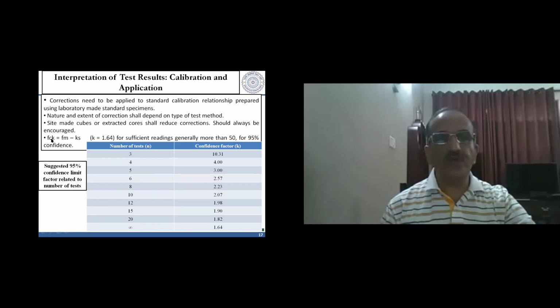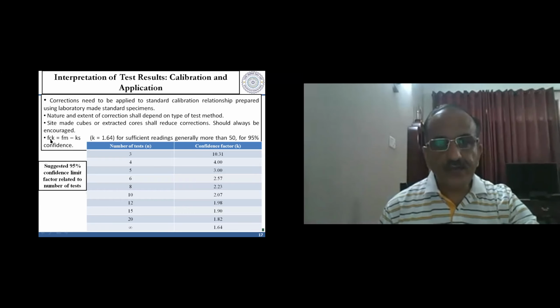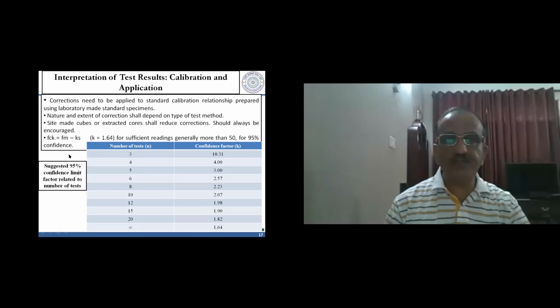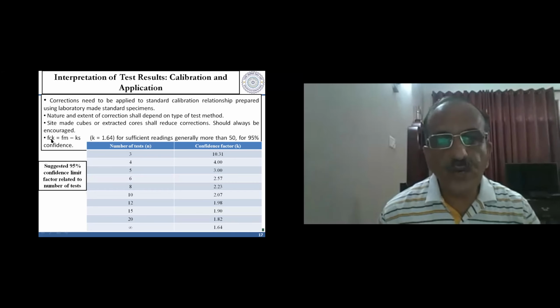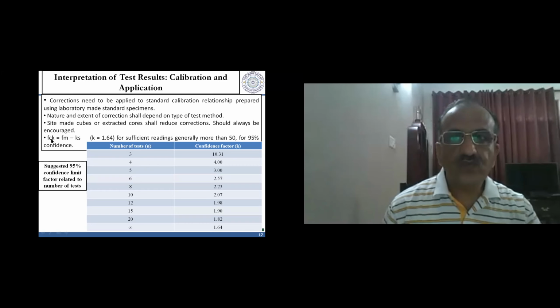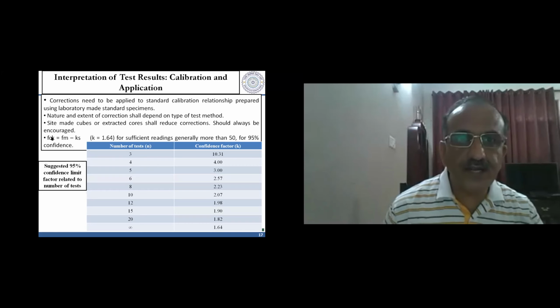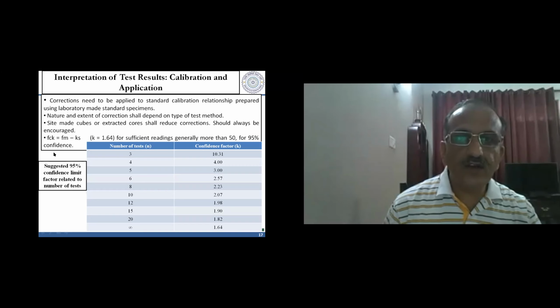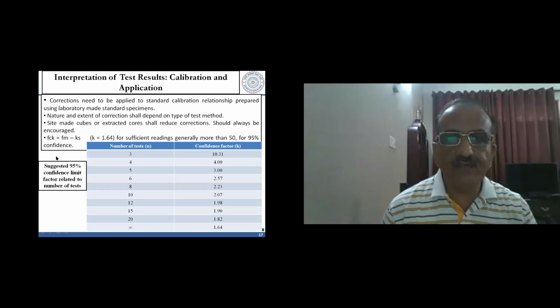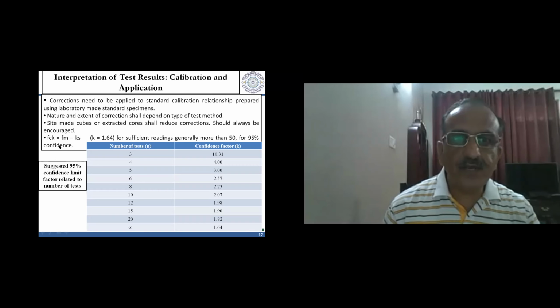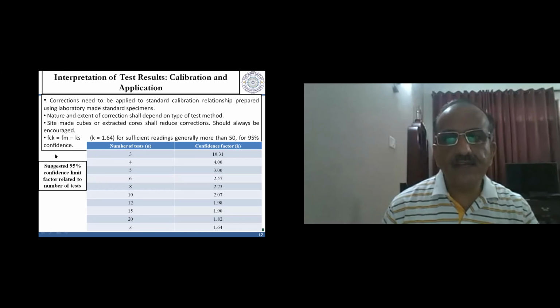Once FCK has been found, you will come to know FCK of in-place strength. Now, acceptance criteria: you have to compare this with the one which is specified. For example, specified was M30, and now you are getting it to be 28. It is not failing, because here you have to apply your judgment, knowledge of the variability of the concrete, and all those things which we have talked about in the previous slides. Difference between standard specimen and field conditions, all those things are to be kept in mind. And there is some guidance given in the codes or guidelines, ACI 228 guidelines or other codes.